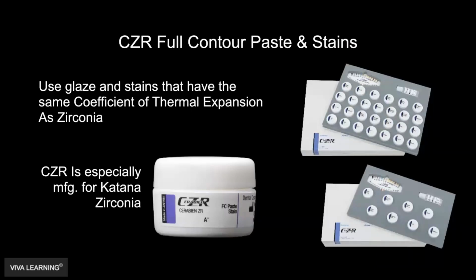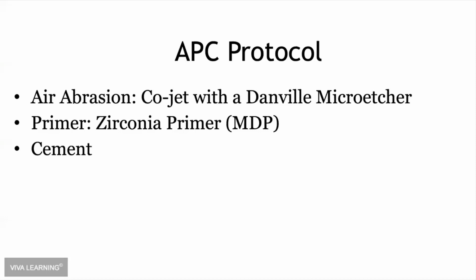We can get some really cool effects if we also do some CZR full contour paste and stains. But we do need to fire this again once it comes out of the sintering. We cannot do it at the same time. So that is one downside of staining and glazing zirconia. It needs to be sintered first, then a separate cycle, typically 10 to 15 minutes, to get this glazed.